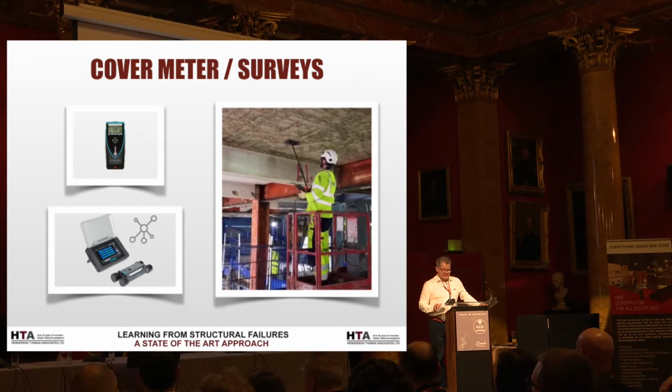These were 3 or 4 metres by 3 or 4 metres. So, in essence, we had to test 450 slabs. Now, if you'd have done this with a conventional handheld cover meter that you can see on the top left, we would have been there for months and months and months. But with the logging cover meter, we were able to basically do 2 very quick scans in both directions over the slab and then do a small breakout to calibrate the readings. So months and months of work were cut down into, I think it was about 2.5 weeks.